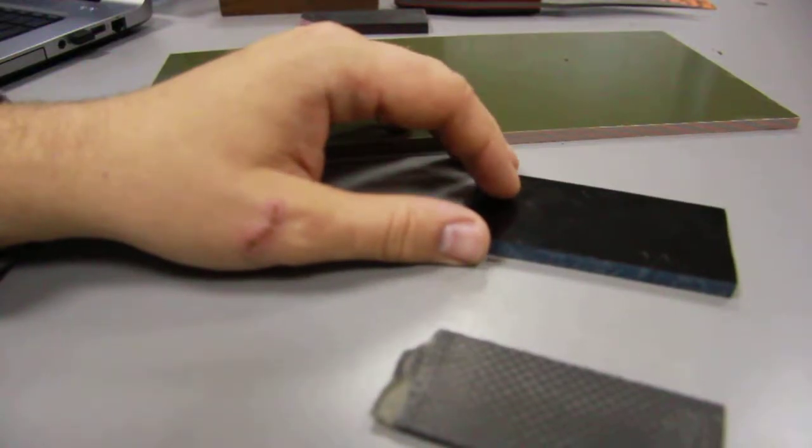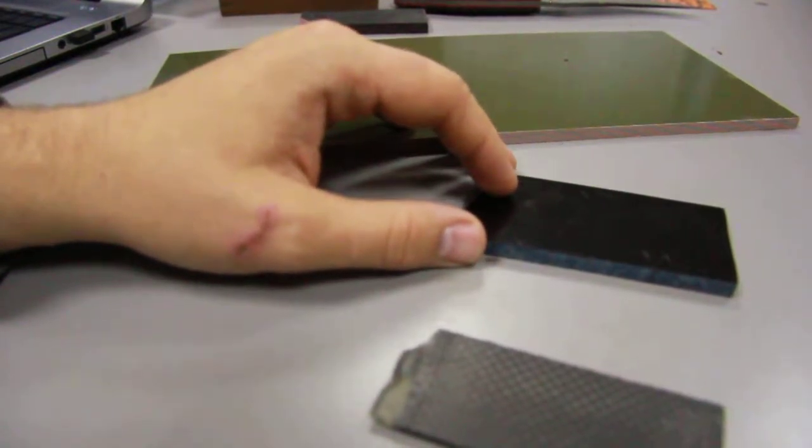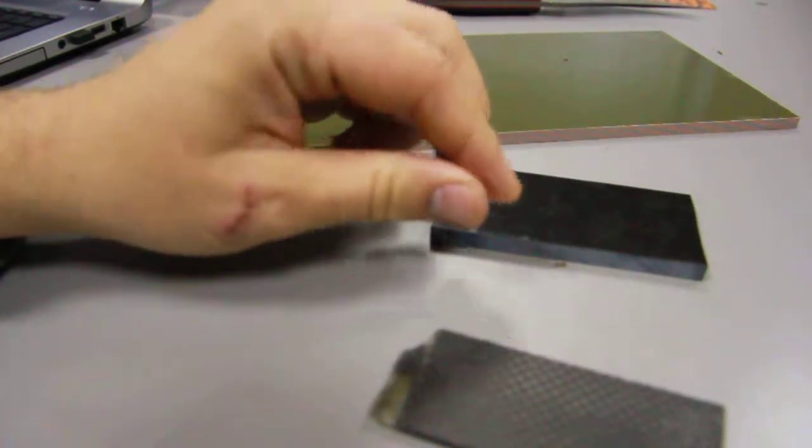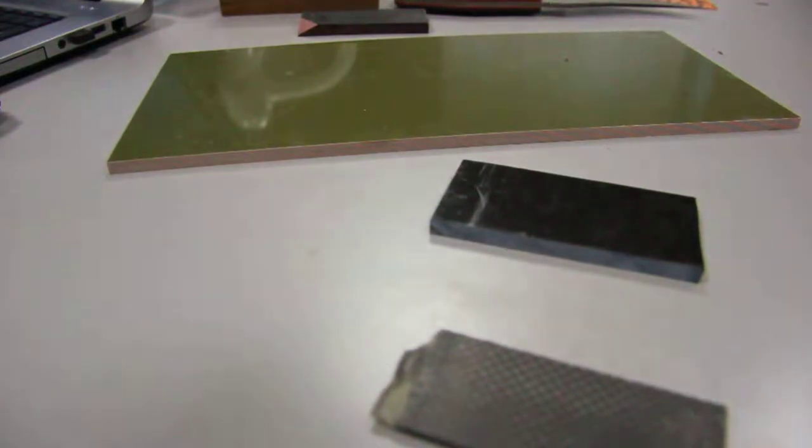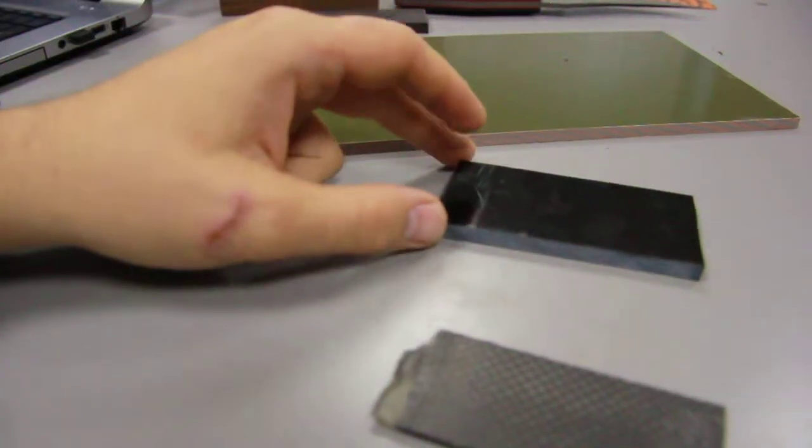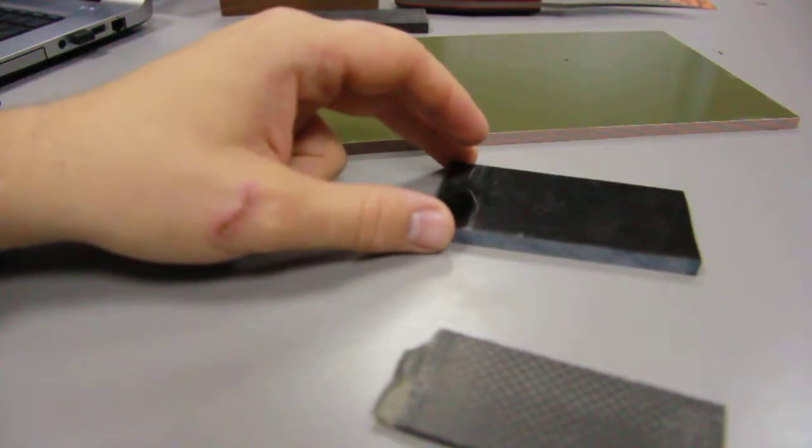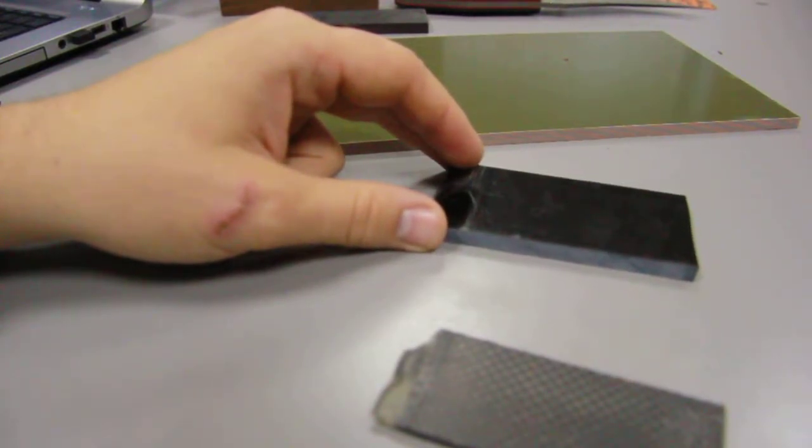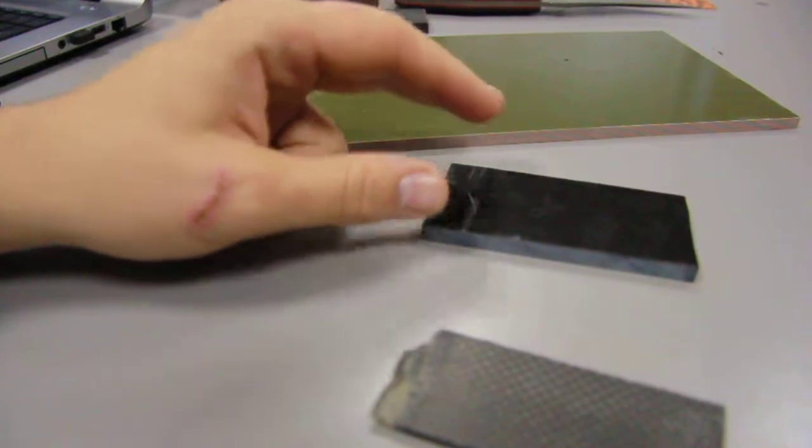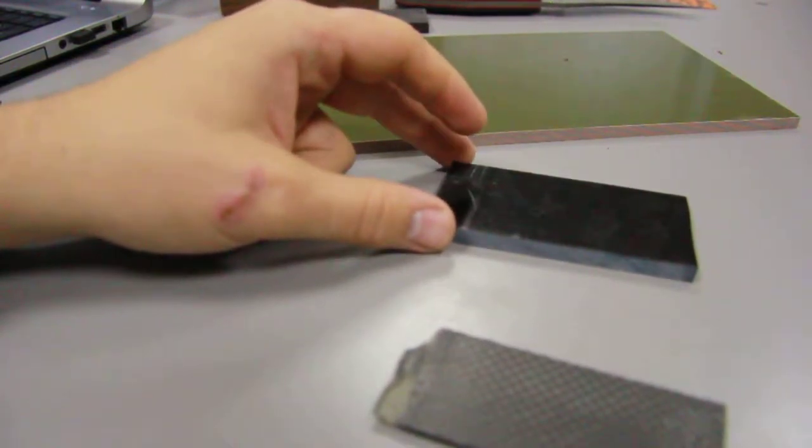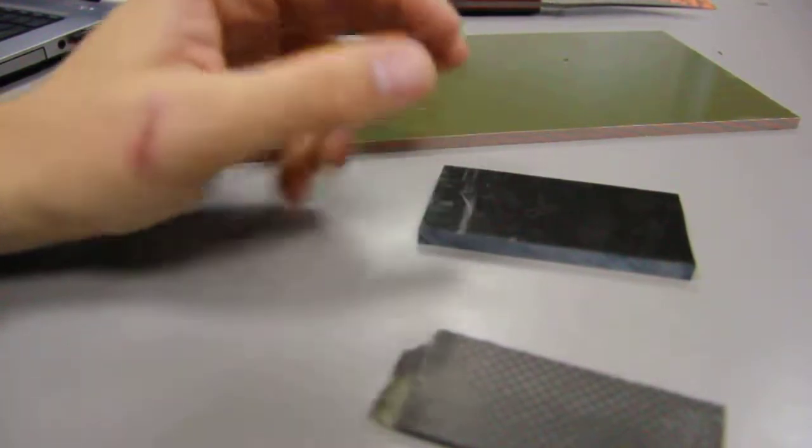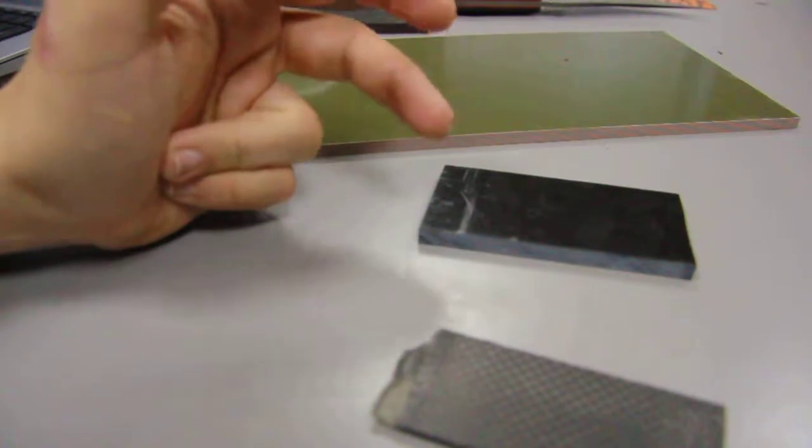The whole thing about glass cloths is actually high-tech and very differential. G10 FR4, which is the full name of this material, is a sort of electric insulation made of electrical grade fiberglass, which is normally E-glass. Compared to other glass fibers, it's relatively not as strong, but it mills very well, has a very good polish, and is strong and very resistant to heat, salt, and chemicals.